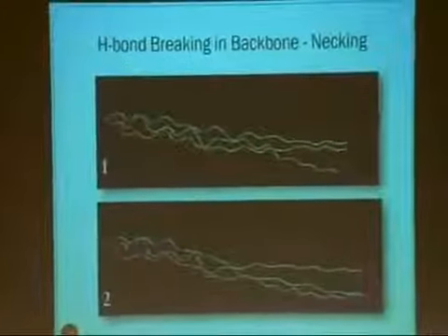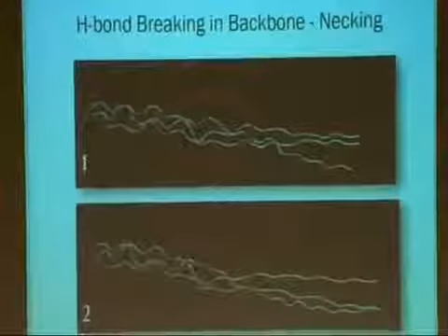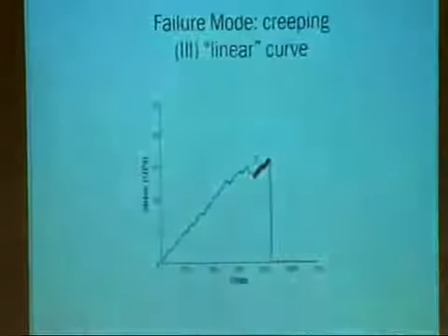The next failure mode is necking, and necking is defined as excessive plastic deformation. And during this phase, here showing the plateau, the backbone of the collagen stretches and deforms very drastically, meaning that a large amount of hydrogen bonds break. And this breaking of the hydrogen...